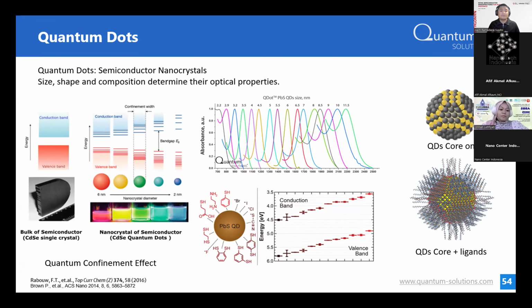To give an overview, a quantum dot is a semiconductor nanocrystal, and the size, shape, and composition determine its optical properties. In germanium tin, you change your material properties by changing the alloy. Here, you have more degrees of freedom because you can change the size of your nanoparticles, your quantum dots. And then we have a ligand at the interface that also tunes how the quantum dots interact with each other.